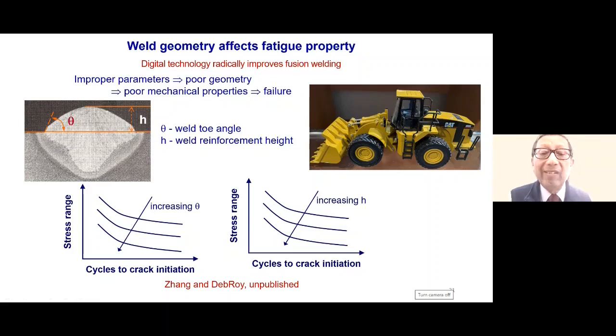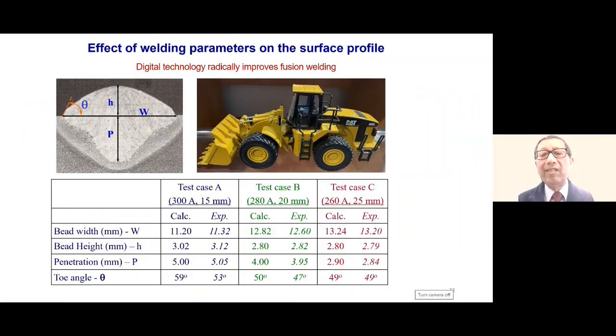How do you increase fatigue life for this material? You decrease your angle theta. Basically, you change the toe angle and the reinforcement height. That is exactly what we did. We did simulation and we showed that before they do the welding, we can tell them what's going to happen if they did the welding.